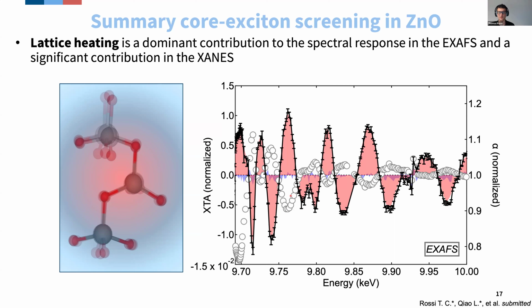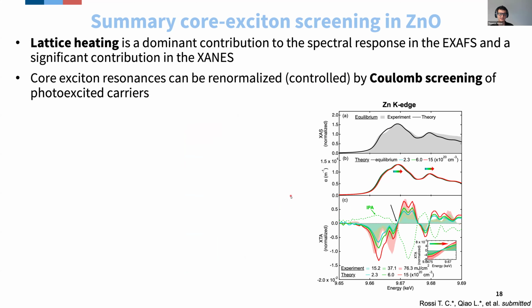And I think this is key for the future of picosecond experiments on semiconductors. Then the other thing is we found out this core exciton screening. And we believe that this could be one way to manipulate core excitons, although on the picosecond timescale, it's quite limited, because what you do is you're basically shifting all these excitonic resonances by the same amount in the same direction. So you are basically modulating your entire spectrum. It's not like you're able to control individual excitonic resonances, basically. But it's still, I think, one contribution to the field of excitonics.